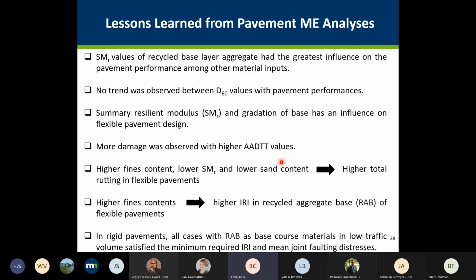But I think, based on, I didn't show all this data, but in the report we provided all in detail, the resilient modulus value of these recycled aggregate base layers is the most influential, and we didn't observe any relationship between the test values and their pavement performances. And with the flexible pavement design, there is a significant relationship between the gradation characteristics of these RAP and RCA materials and their resilient modulus values. And as expected, higher traffic values cause more damage.